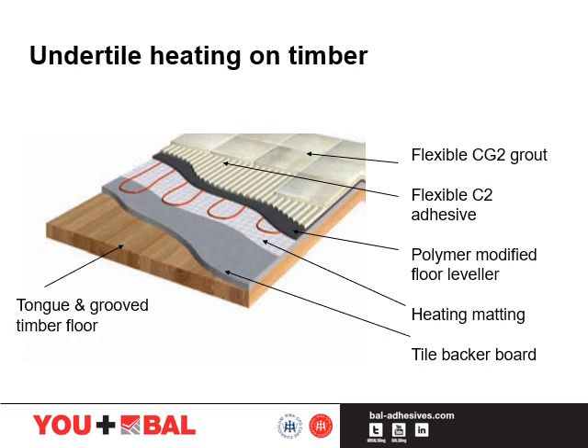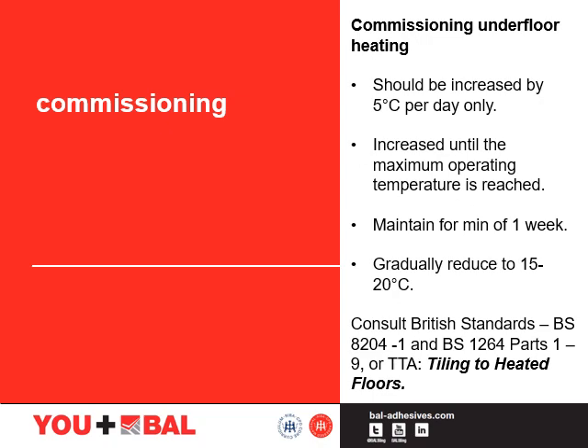Again, the specification in terms of adhesive and grouts call for a minimum C2 tile adhesive and a minimum CG2 grout. Highly polymer modified products, especially ones with rubber crumb technology, are recommended, together with a polymer modified floor leveler in this scenario. The commissioning of the underfloor heating should be carried out prior to any tiling.